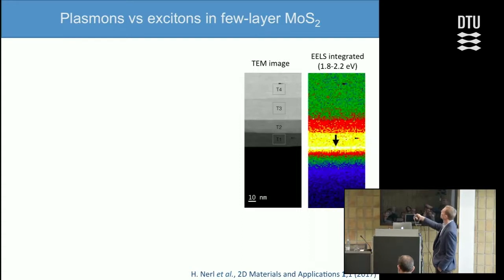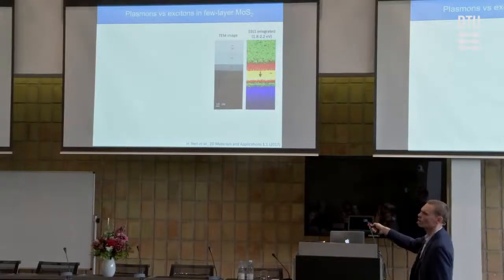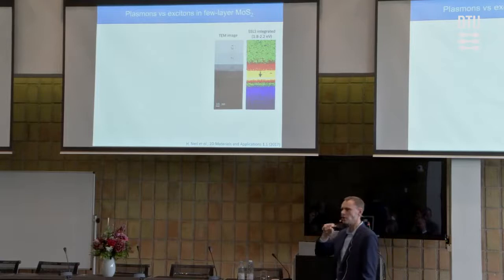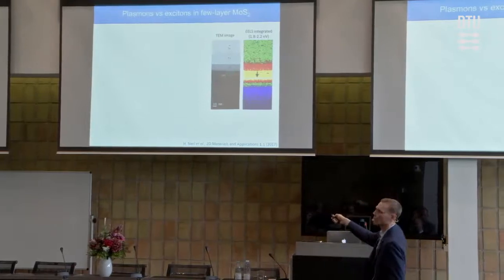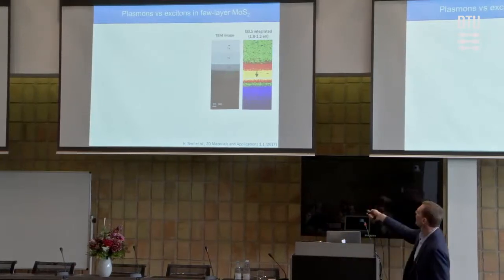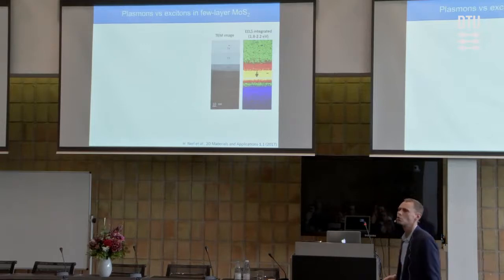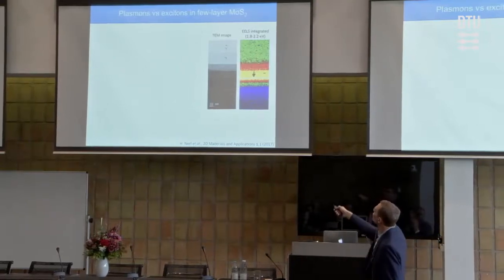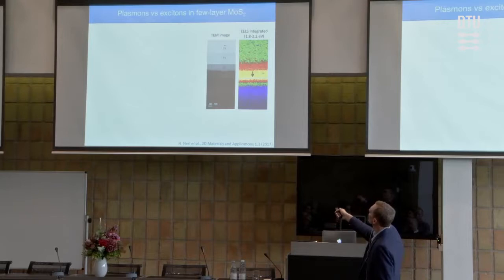So what we looked at were different flakes of MoS2. Here is a sample where you can see from this TEM image different terraces corresponding to different thicknesses of the MoS2. The thinnest are around 3 layers, and the thicker ones are close to bulk MoS2. So this is a TEM image, and over here is shown EEL spectra.